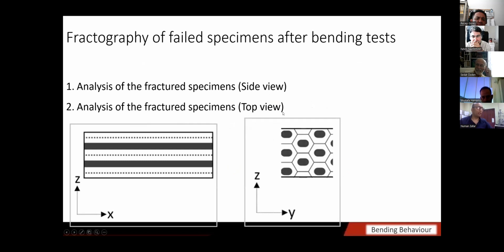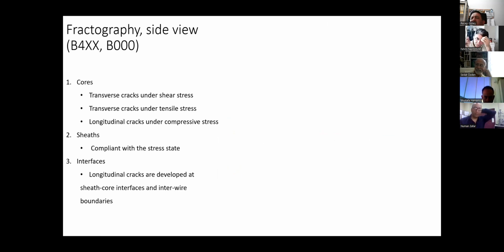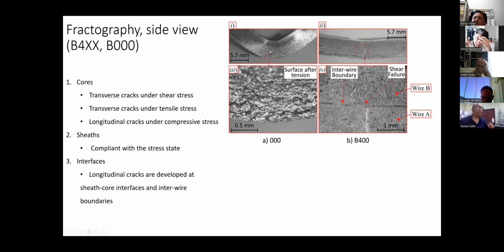So I have studied side views for the fractography and the top views with the electron microscope. These two types of views, which we have studied for the fractography, are interesting to see. After the bending, this specimen was elongated very high. There are no cracks formed here, but the surface shows a material which is subjected to tension. A typical steel, after tension, tends to show a structure like this.